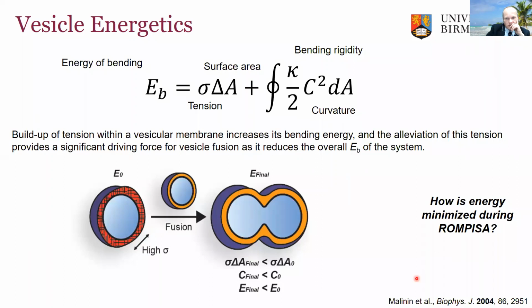And again, this may be because, as you might remember, I said that we have an extremely fast polymerization. So you can imagine that our vesicle membranes are becoming charged with high tension as the length of their polymers increases, as I said, to try to compensate for the static curvature and surface area. So we're getting this build-up of tension, and we propose that the alleviation of this tension is the driving force for vesicle fusion. As I said, it reduces the energy of bending of the system.